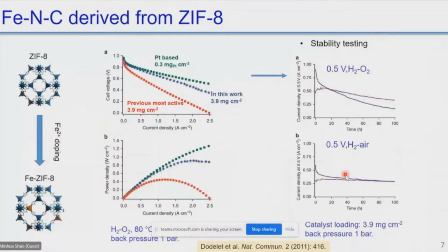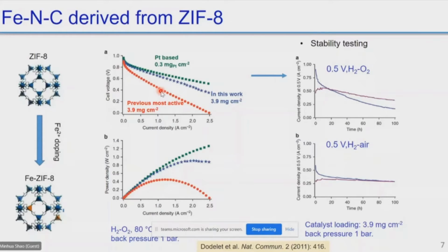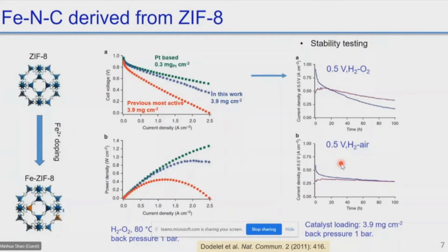Okay. So another way of synthesizing non-precious metal catalysts: back in 2011, we found that we can use ZIF or MOF as basically a template. Then we can dope with a small amount of iron and do heat treatment. So iron will stay in this MOF, and the MOF itself will become carbon black, basically a nanoparticle. You can see the performance of this material is much better than previously synthesized non-precious metal catalysts, and it's very close to platinum. But if you look at the stability, both materials did not show good stability. If you cannot solve this durability issue, it cannot be used in a real fuel cell.